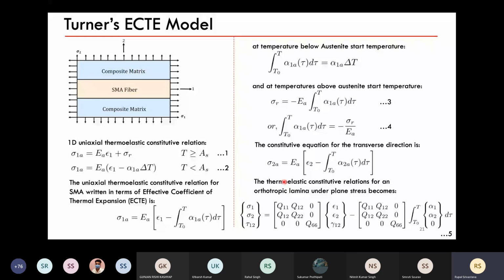But the interesting part with shape memory alloys is that when we increase the temperature, it is shrinking. So it is an effective coefficient of thermal expansion, but in this case, it is contraction. So here you can see that when temperature is greater than austenite start, our material is in its austenite phase, we have this interesting term called sigma R, which is called recovery stress. This term was given by Turner, and it's the stress which is generated by the shrinking of the wire.